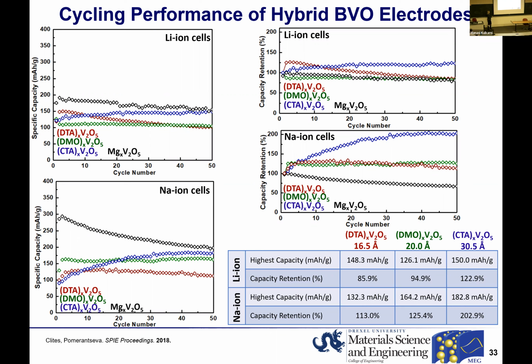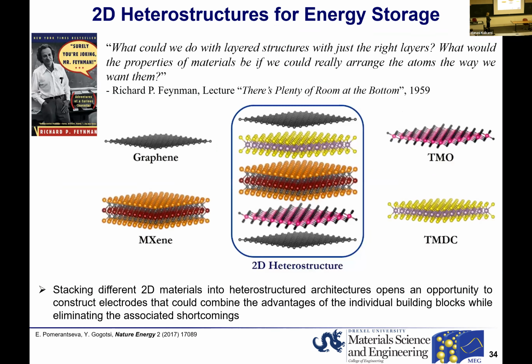So in fact, the organic molecules occupy a lot of space, and they prevent ions from being intercalated in large amounts. And that leads to capacities that are essentially lower than those we achieved in the case of the magnesium pre-intercalated material. So the take-home message here is that just expansion of the interlayer region will not result in a material with very high capacity. There are other factors that need to be taken into account.